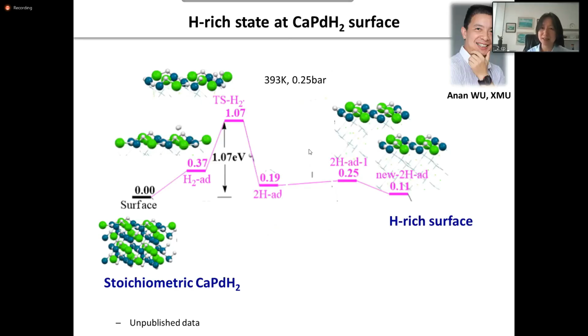in collaboration with Professor Wu at Xiamen University, we found a very interesting phenomenon. What is that? If we look at the surface of CaPdH2 and add hydrogen onto that surface, of course we have to encounter a 1.07 electron volt kinetic barrier, but we could have a surface state with a hydrogen-rich surface. This is information that motivates us to think that at the surface, the driving force for chemistry would be somehow different from the bulk phase.